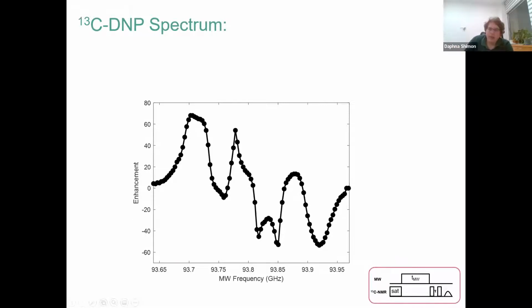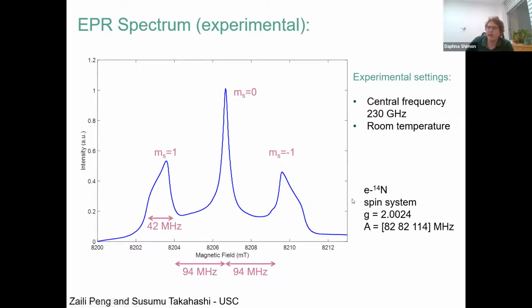And here, when you look at the carbon DNP spectrum, there's just really a lot of things happening. There are a lot of features, and it's not fully obvious when you look at it what's going on. So the best way to decide what's going on is to measure the EPR line. And so we worked with Susumu Takahashi at USC, and they measured the EPR line of the diamond powder at room temperature at high field, 230 gigahertz.